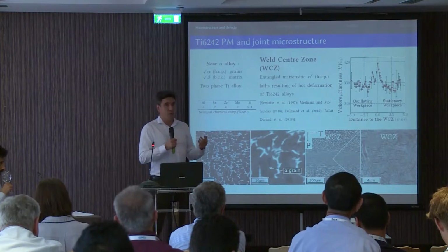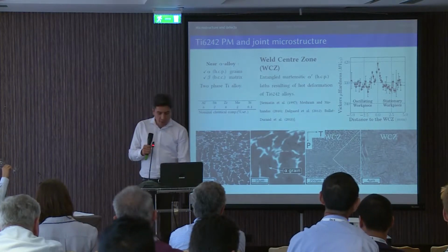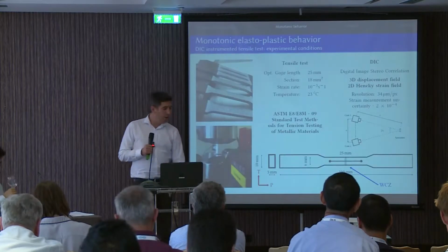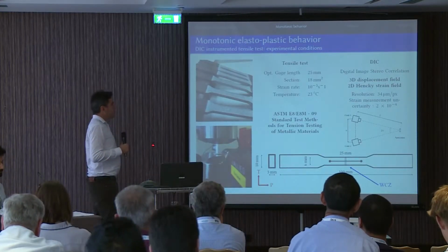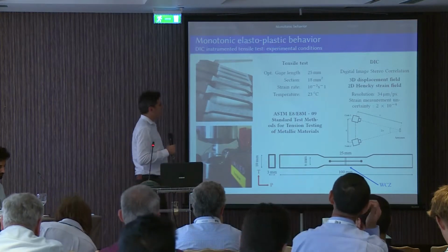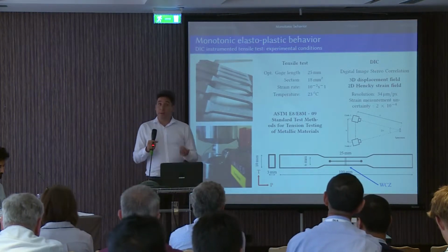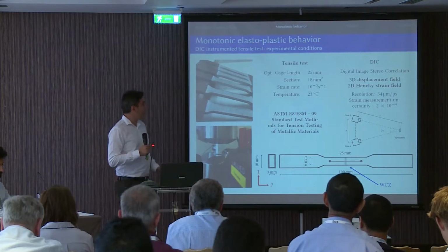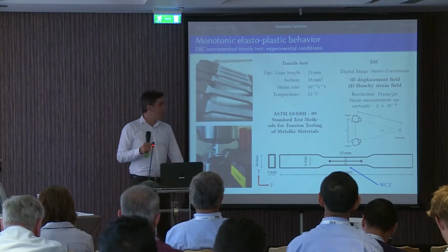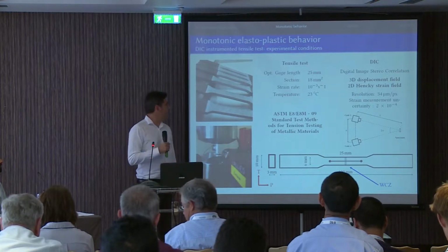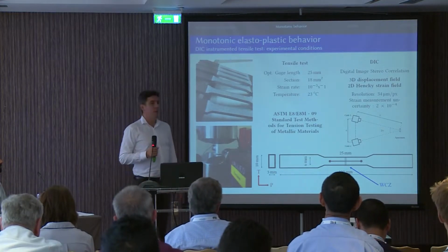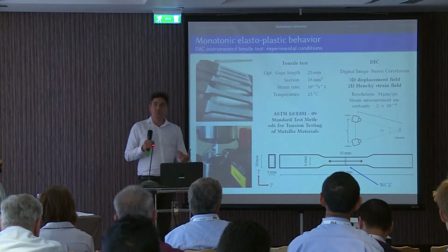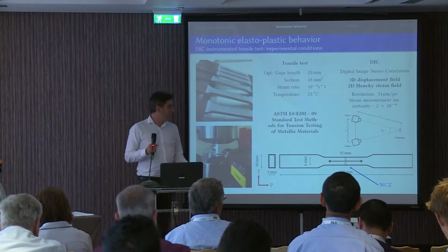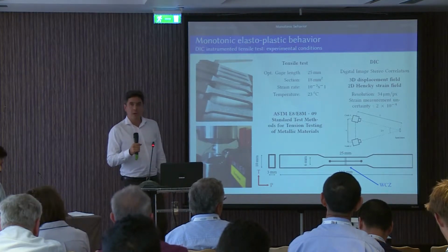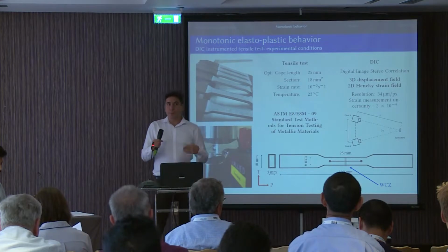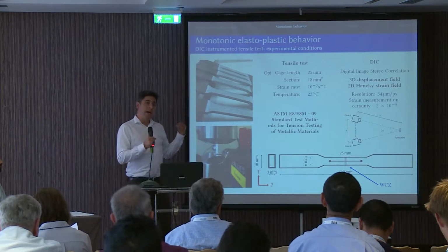So if we were to do a tensile test, we should wonder where the fracture should take place. Here are the tensile samples: parent material samples and cross-welded samples. We have a gauge length of 25 millimeters and a cross-section of 15 square millimeters. We have instrumented the tensile test with a strain monitoring system. If you do not know this technique, don't worry, I will be very happy to give you details about it at the end of the session.